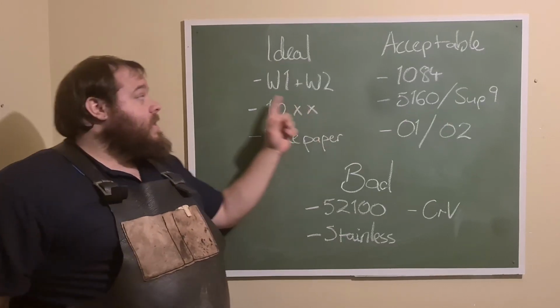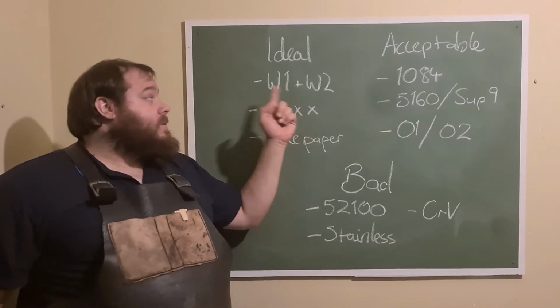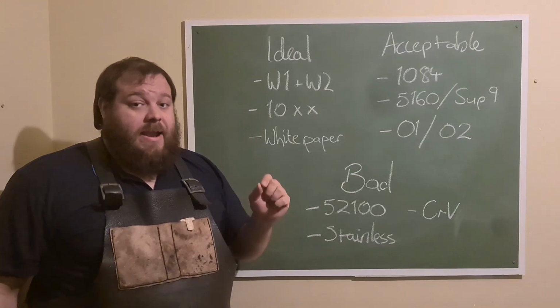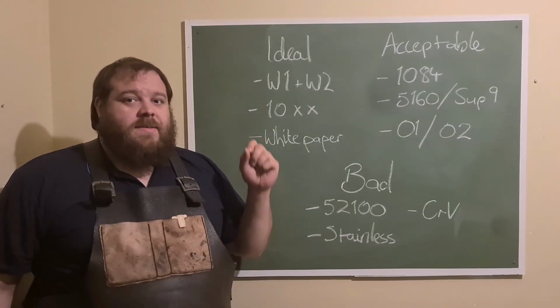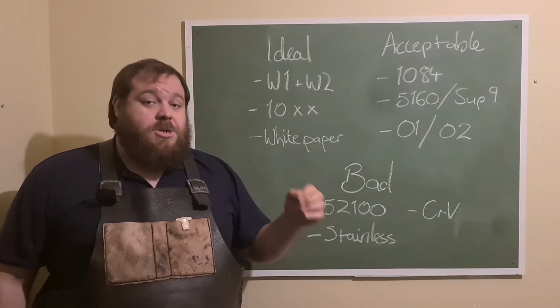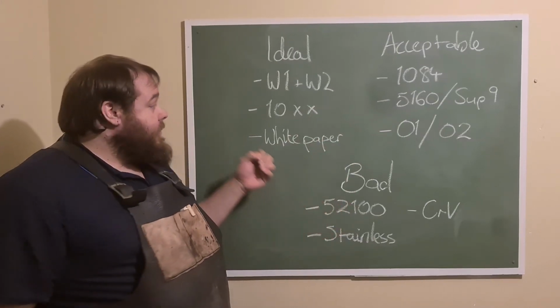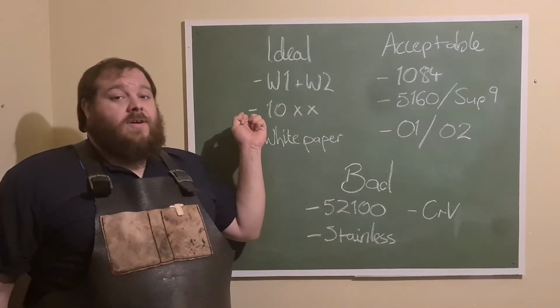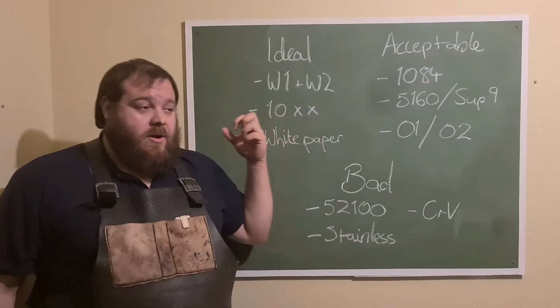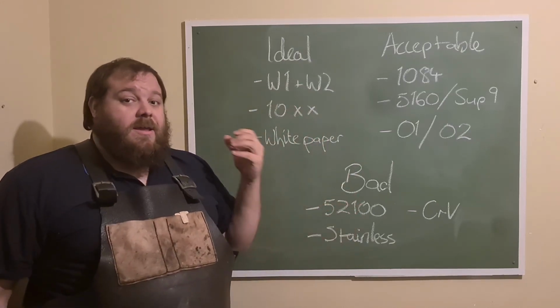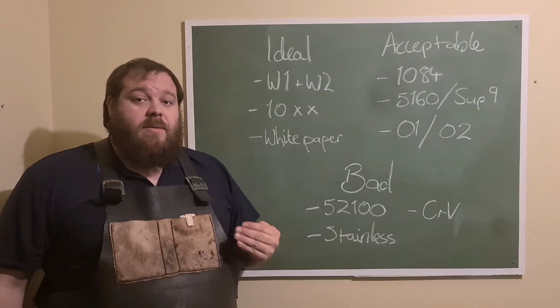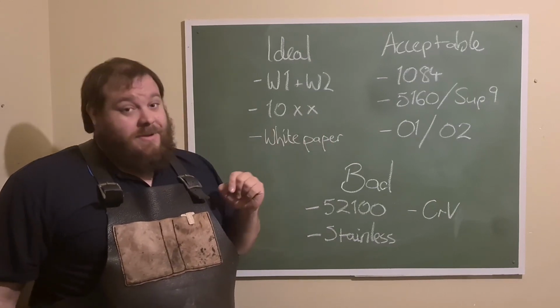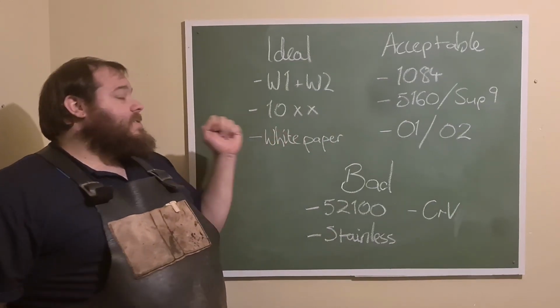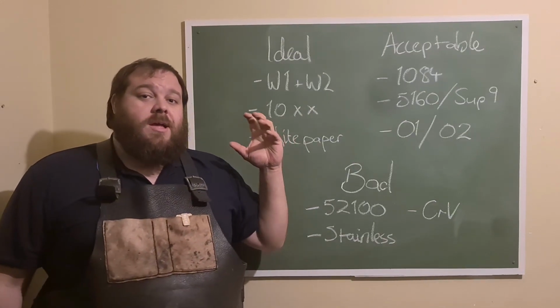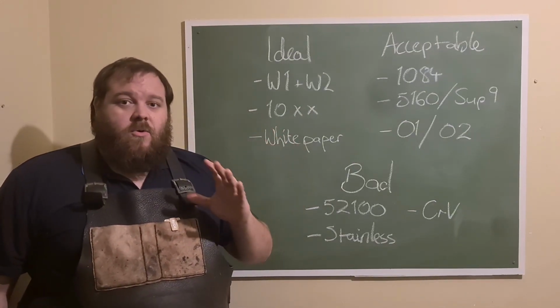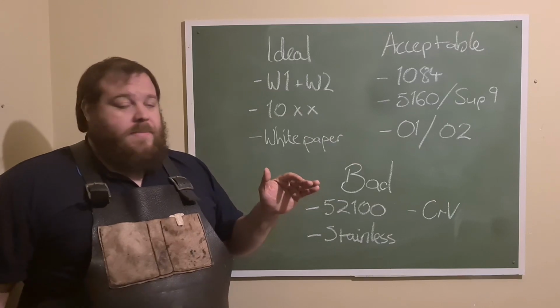Of the two, W1 has the lowest alloy. W2 has a very small amount of vanadium in it, which can increase the speed at which, the depth at which it hardens. Then we have the 10 series steels. Now, most people will know at this point that 10 series steels are simple carbon steels, with the exception of one, which we'll get to in a second. But the 10 series steels are pretty much the guaranteed ideal for Hamon making in general.